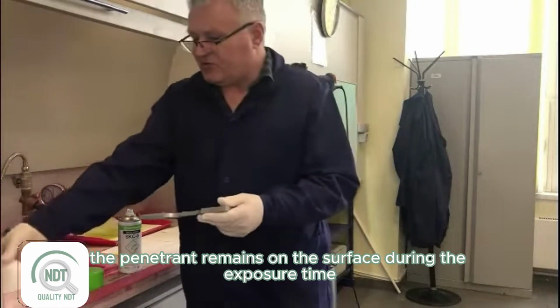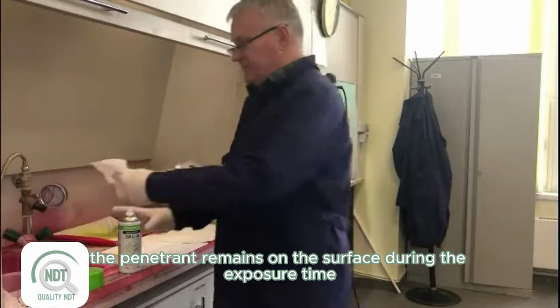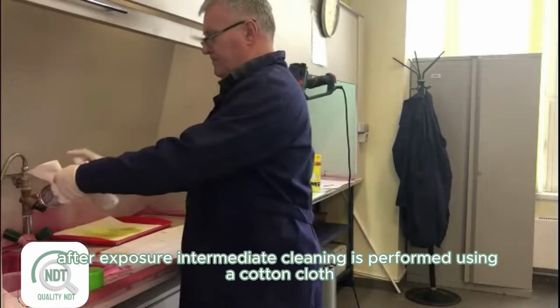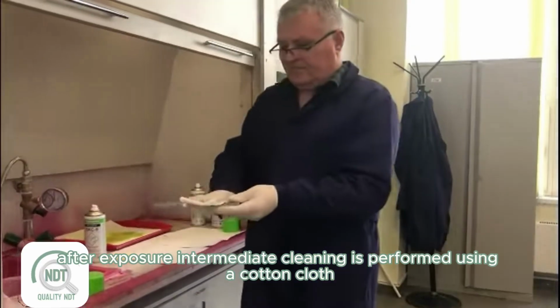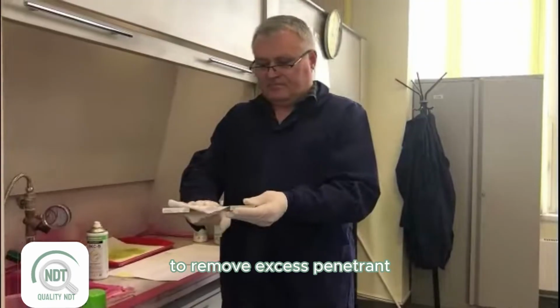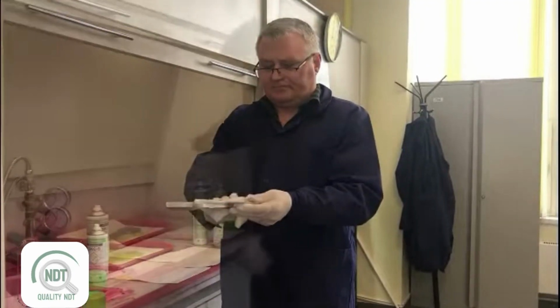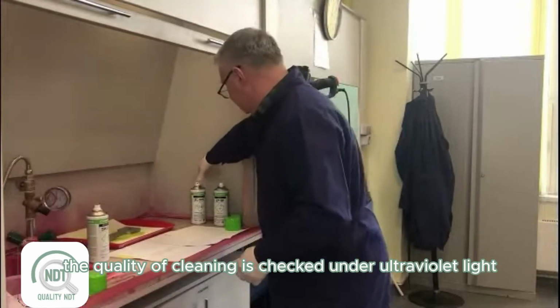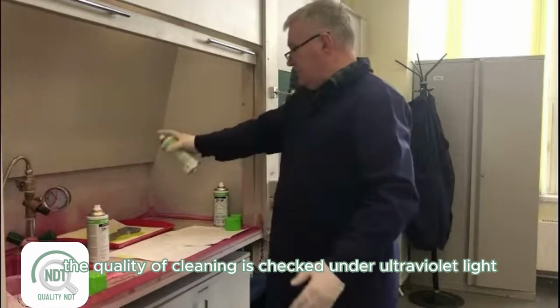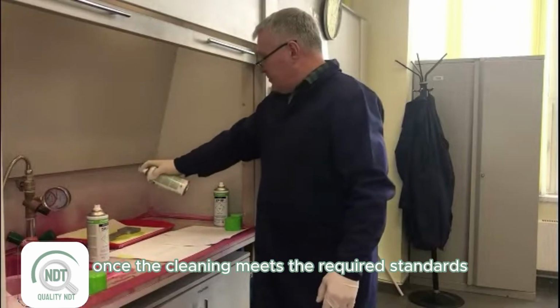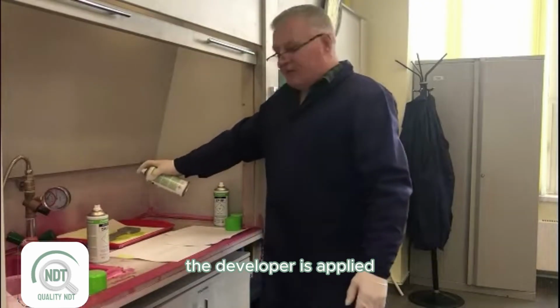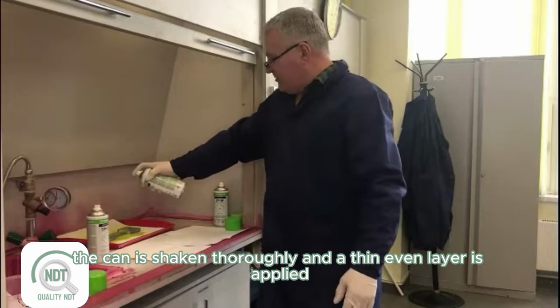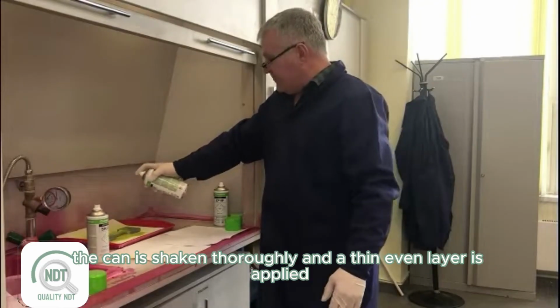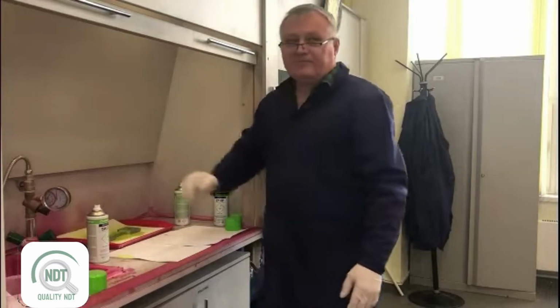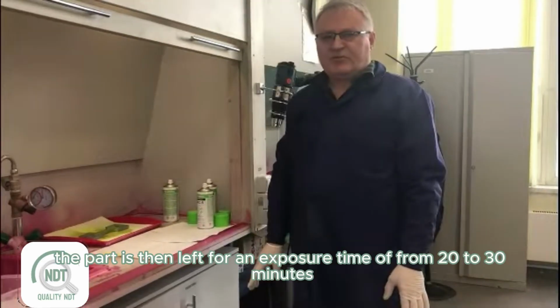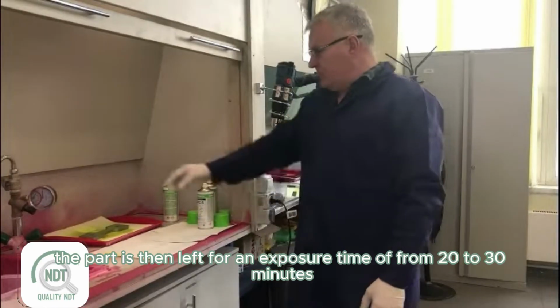The penetrant remains on the surface during the exposure time. After exposure, intermediate cleaning is performed using a cotton cloth to remove excess penetrant. The quality of cleaning is checked under ultraviolet light. Once the cleaning meets the required standards, the developer is applied. The can is shaken thoroughly and a thin, even layer is applied. The part is then left for an exposure time of from 20 to 30 minutes.